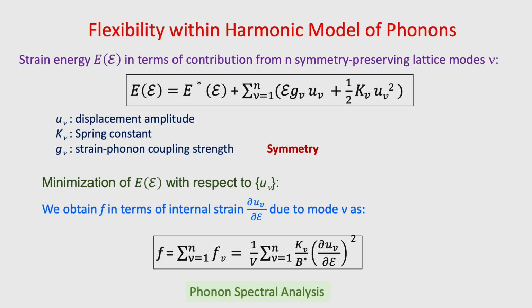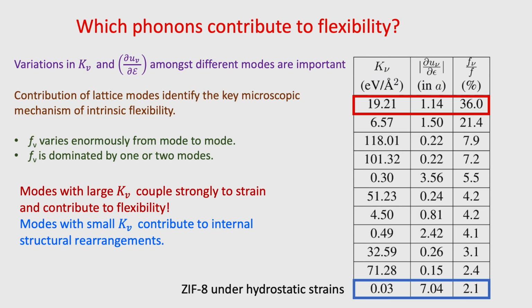to flexibility. Now with this, we can even point out which vibrational modes are responsible for greater flexibility of a given crystal. And using this, we find a very counterintuitive result. Typically, people used to believe that it's low frequency soft phonon vibrations which dominate flexibility. What we show is actually soft phonons and relatively hard phonons have to work together to give you high flexibility. You will see this is ZIF8, and this phonon dominates.